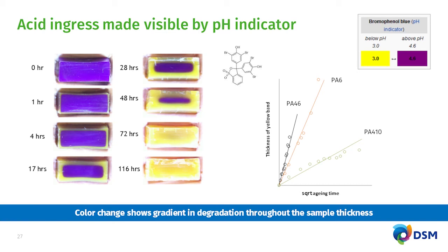So we do this for different types of polymer, and you can see that for polymer like polyamide 4,6, the ingress of acid is much faster than for less polar polyamide like polyamide 410. So this is also indicating that by changing the molecular structure, by changing the polarity of the polymer, you can also, in the long run, limit their degradation via limiting the ingress of the active species itself.